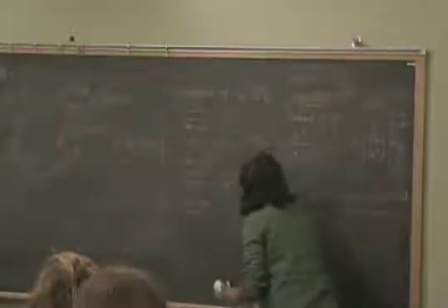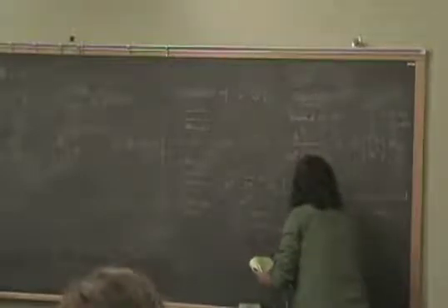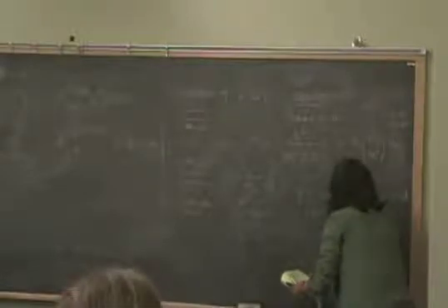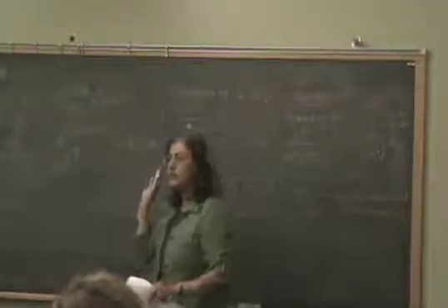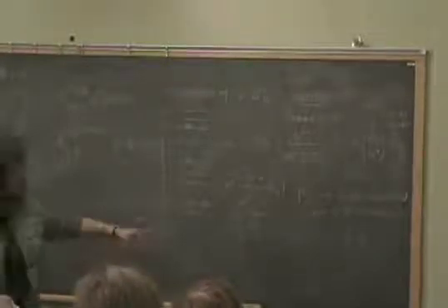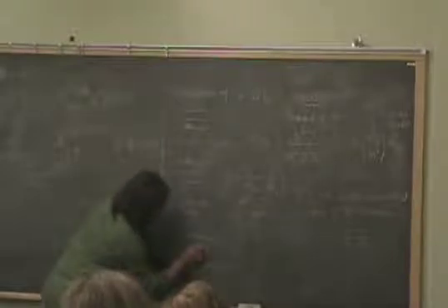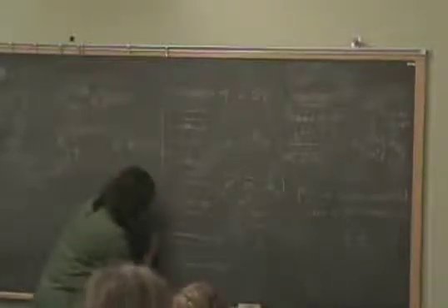From this bound radius, you can also calculate a binding energy, E excitation, and that will turn out to be 13.6 eV times something or the other, m star over m, 1 over epsilon squared. So the main point about this is that you will get absorption or emission below the band gap. Suppose I was just looking at excitations even in the bulk semiconductor. You have a band gap, but because you have an exciton bound state, that means you have a state available below the gap by this much. This is the binding energy. So here is the valence band, conduction band, and there's some excitation energy, which can be anywhere in the gap. And this difference is E x.